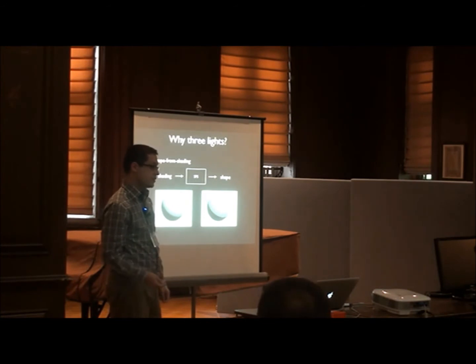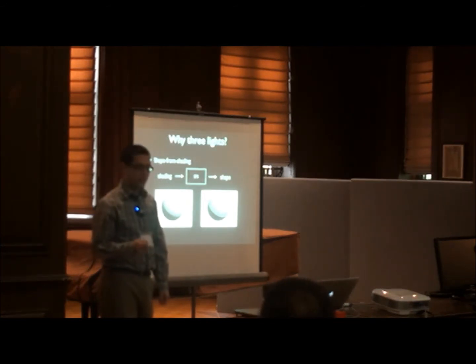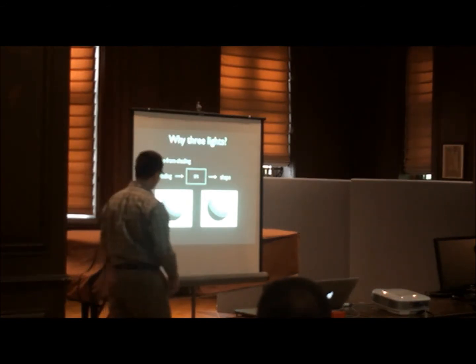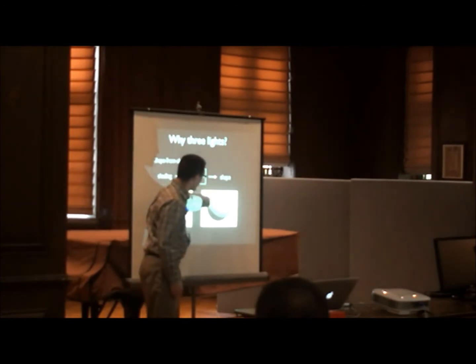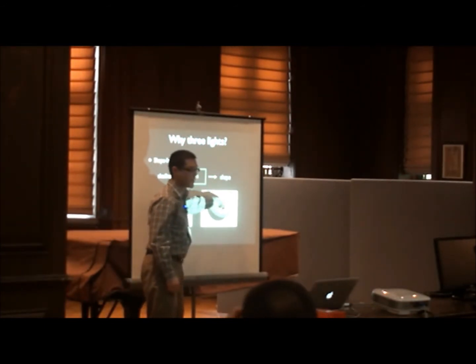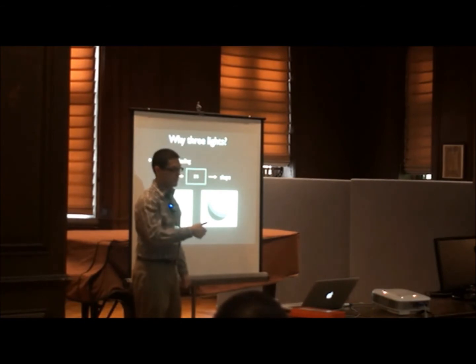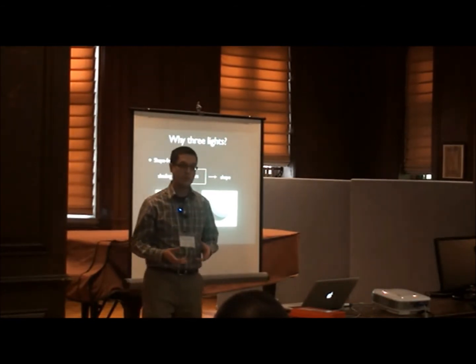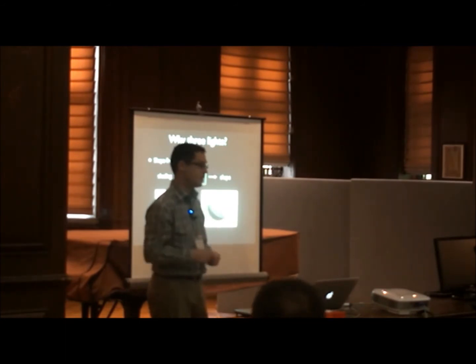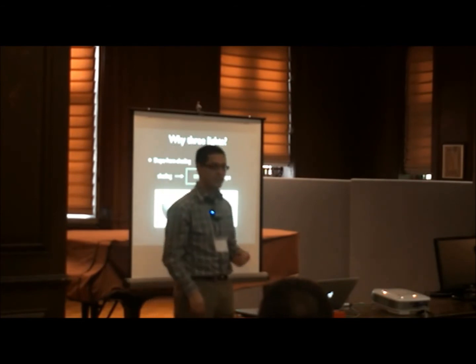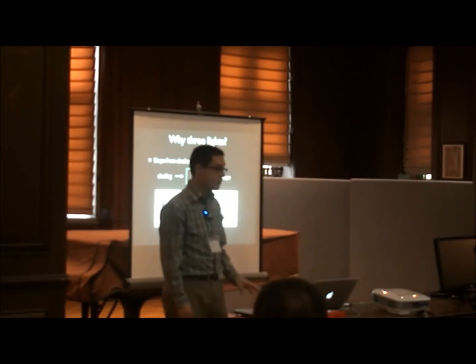So it's fundamentally ambiguous. If you encounter that 0.8 intensity value, you can't know where you are on that whole circle. It could be any of those orientations, so you really don't know that much about this shape. There's still, at least in theory, an infinite number of orientations that you could be. You've constrained it to be on a circle, rather than the entire sphere, perhaps. But that's not enough, and that fundamental ambiguity makes shape from shading a very hard problem to solve with a single light.